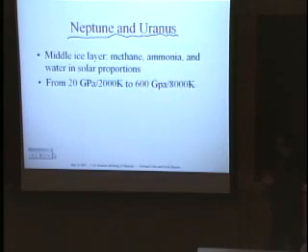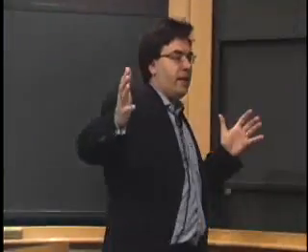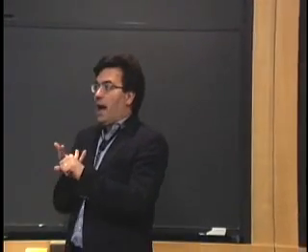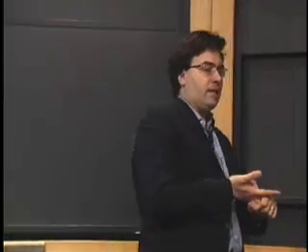We haven't really reached this state. There are indications from the shock experiments that it could reach the metallic state at 350, 400 gigapascal. But this is extremely important because, for a planet like Jupiter, there is a huge difference if we are going to have in the inside of the planet a molecular solid, or a metallic solid, or a metallic fluid. If we have hydrogen that all of a sudden inside is a metallic fluid, well, we can have right away, like in the case of Earth, a significant source of magnetic field if we start to have a circulation in that fluid.